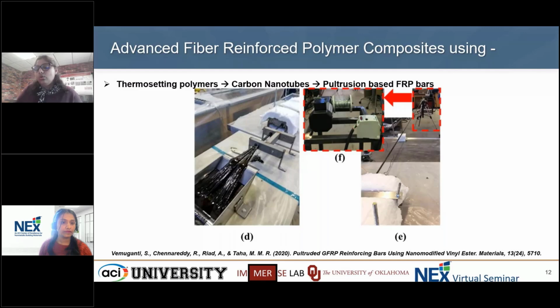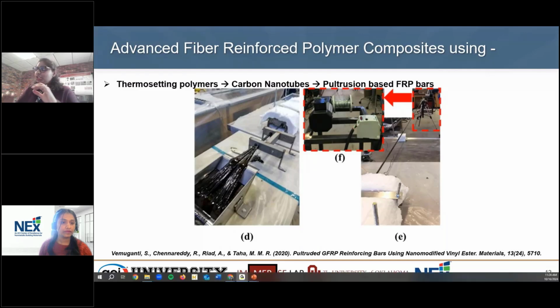Now think about how we can actually remodel or redesign this die to be able to get these orientations of fiber, and they have to be maintained through that entire length of the die and come out with those orientations. That is such a challenging process because however you get the strands, you still have to impregnate them in a resin. When you impregnate them and bring it into a die, you probably have to have another setup where each strand is being oriented in a different direction. But eventually, they all have to come together again.